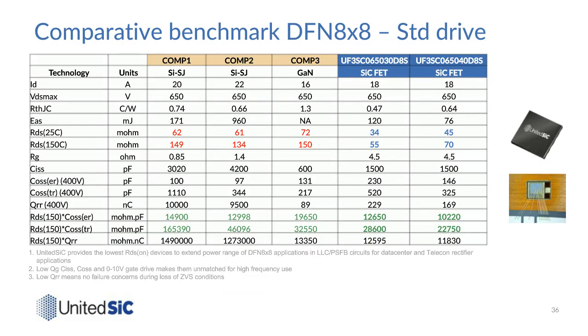And these same low RDS(on) devices make it possible to put these low RDS(on)s into very small packages. So the DFN 8x8, it's an 8x8 millimeter surface mount package. You can see here for the on resistance at 150C, if you look at the red numbers versus the blue numbers, we can provide RDS(on)s half or one third of what's out there from the competition while maintaining, if you look down in the green, good figures of merit for switching as well, the RDS COSS figures of merit. So what you do with this is shown on the next slide here.